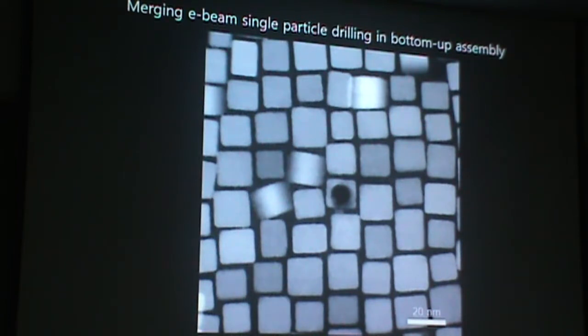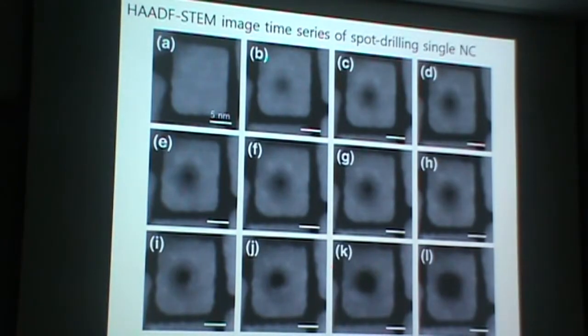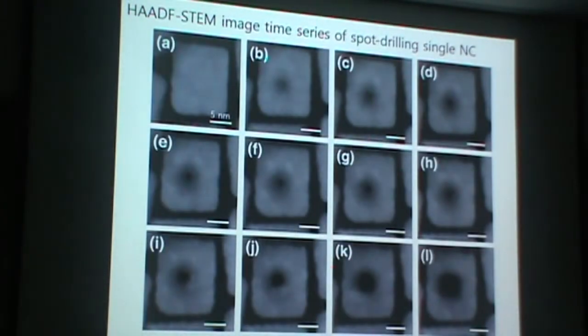So in this study, with our Oak Ridge Labs collaborator, published just last year, we merged E-beam single particle drilling methods with self-assembly of nanoparticles. This is a TEM image time series from 0 to 2 minutes of single spot drilling of a single nanocrystal. We can see that the crystallinity is quite well preserved, meanwhile having specific design-targeted drilled holes in individual nanoparticles, on the scale of even 3 to 5 nanometers.